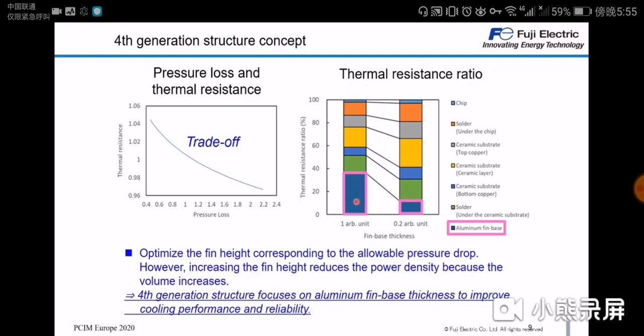This is what we are focusing on right now, because at Fuji we were able to reduce the thickness of this aluminium fin base to 1/5 compared to our 1st generation. This aluminium fin base is the thickness of the base plate in a conventional module. And by decreasing this thickness, we were able to reduce the thermal resistance by a huge margin.